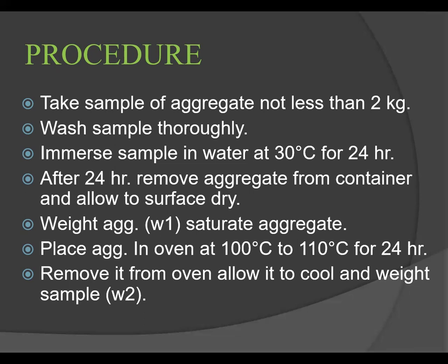After that, the aggregate is placed in a shallow tray and heated at 100 to 110 degrees Celsius in the oven for 24 plus or minus 0.5 hours. After that, it is put in an airtight container and weighed.